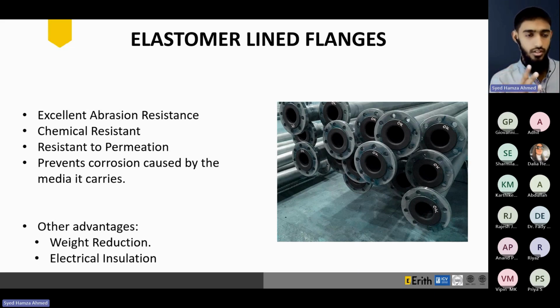At one point or the other, the connections are going to be opened up, and this is a challenge that is continually faced in rubber-lined, elastomer-lined flanges. The challenge then becomes selecting a gasket that will prevent sticking and tearing. Again, many polymer and rubber-lined pipe manufacturers recommend assembling the flanges without a gasket, sealing one liner against the other. The gaskets are typically recommended for these lined pipes if they are mated to a valve or to a line pipe flange, or if a joint is opened and reassembled.